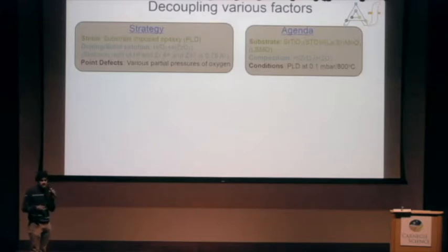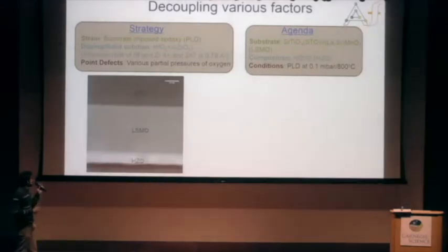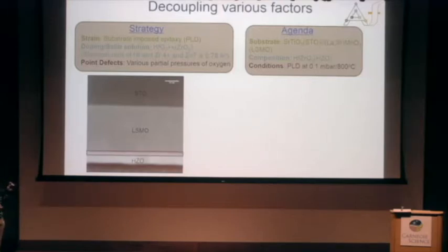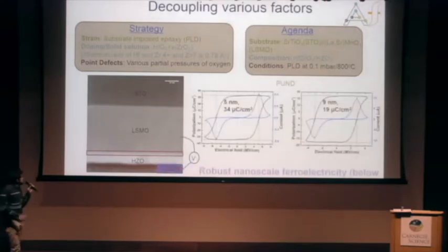But what I'll show you in this talk is just one substrate, which is STO with LSMO as a back electrode, one composition, which is 50-50 of hafnium and zirconium, and the conditions optimized for growth of these films. So the stack looks something like this. It looks nice. But if you have a keen eyesight, you could recognize that at the interface of LSMO and HZO, something strange is going on. We will come back to this.